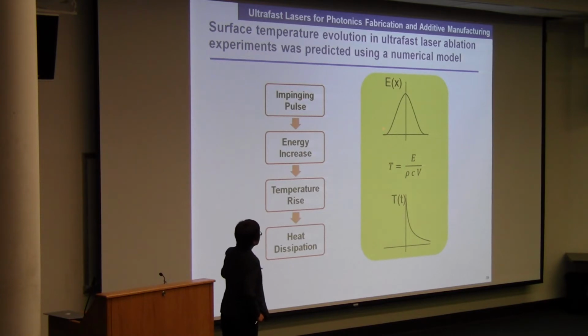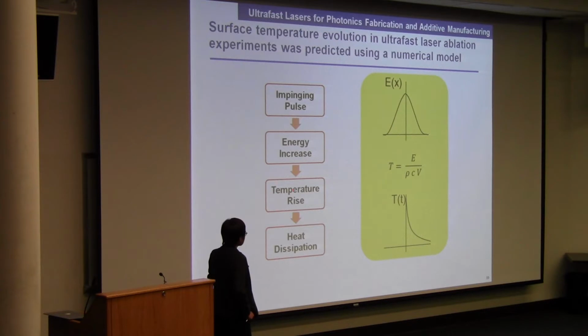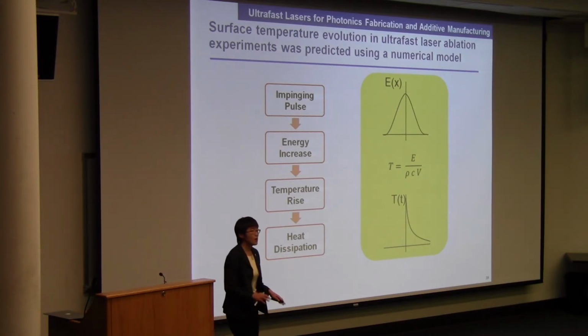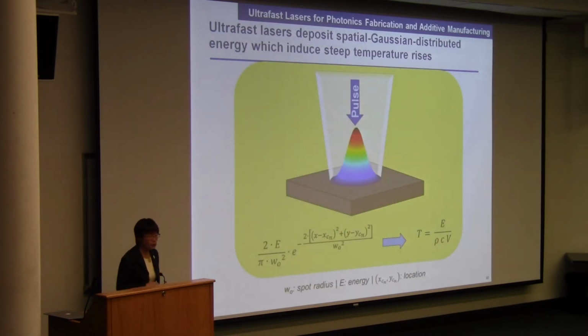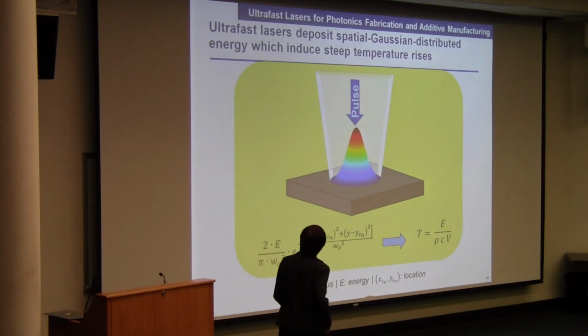You have an impinging pulse that has a Gaussian profile, and with a Gaussian profile energy. And with the deposition of the laser pulse, you have energy increase, and there's a direct relation between temperature and energy. It's related to the material density, thermal capacity, and volume. And this temperature rise causes heat accumulation, and then there's a heat dissipation process. Now this is the material science and thermal part of the understanding. So the ultrafast laser deposits a spatial Gaussian distributed energy which induces steep temperature rise. And this energy can be represented by a Gaussian pulse centered at x0, y0. That's directly related to the temperature.